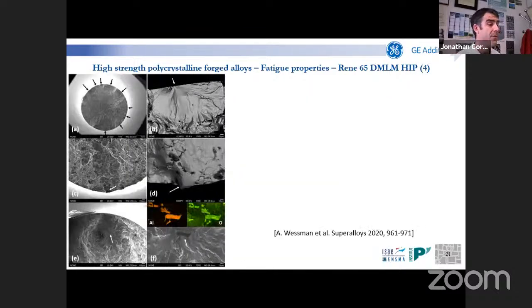From the point of view of crack initiation, we observe almost the same crack initiation as for the cast and wrought material, meaning surface crack initiation at this temperature. That's really typical. We have crack initiation at twin boundaries assisted by oxidation. And very occasionally, we obtained crack initiation from an internal site at a non-metallic particle, typically an alumina type particle coming from the processing of the powders. Most probably, I don't have all the details on this.